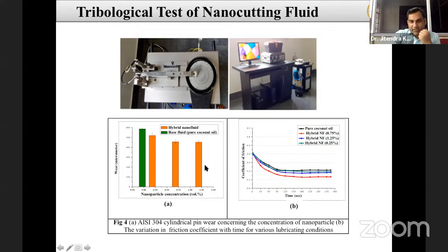And wear analysis also shows the same thing. We observed it in microns, and 0.75 gives the better result. But after adding the hybrid nanoparticles in the base fluid, the friction is always less than with the base fluid alone, and that's why the wear is also less.